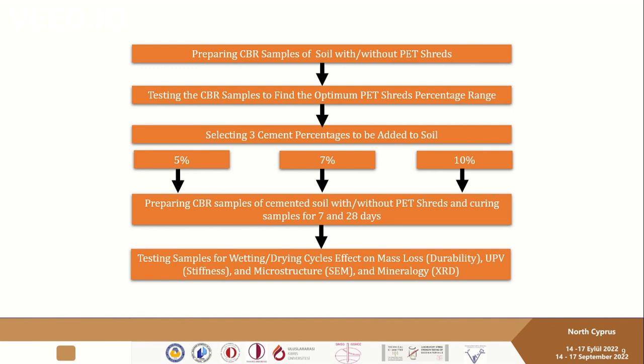And after that, CBR samples of soil with and without PET shreds were prepared to find the optimum PET shreds percentage range to be used to reinforce the cemented soil. And after that, three different percentages of cement were selected to be added to the soil, which were 5, 7, and 10. After that, the CBR samples of cemented soil with and without PET shreds were prepared, and then they were cured for 7 and 28 days. And after curing, the samples were tested for durability, stiffness, microstructure, and mineralogy.